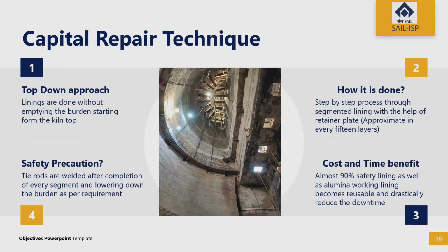And one more thing I would like to highlight is that we have also changed the capital repair technique. Usually in most places during the capital repair of the lime kiln, we empty the burden completely and dismantle all the bricks, and start lining from fresh. In that process, time is a factor. Almost 2 months it takes for a full repair of the lime kiln. It is also a wastage of refractory, because during the dismantling we lose almost 60 to 70% of the insulation material or safety lining, which is already intact. We can reuse it, but we are unable to.